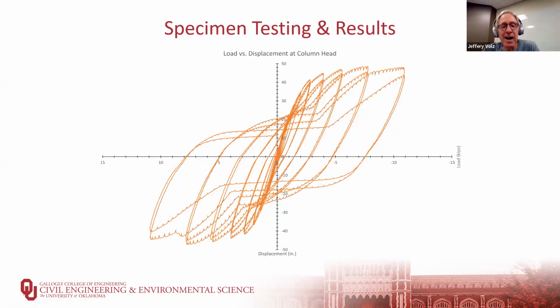The UHPC column, which is identical to the SCC column in terms of the steel tube and the FRP tube, the only difference is the concrete. The SCC has a compressive strength of 10 KSI. The UHPC has a compressive strength of 20 KSI, but also has steel fibers, which increase the tension capacity. So it's going to provide better confinement. It's also going to take some tension. And it showed this by not having a deteriorating stress strain diagram.